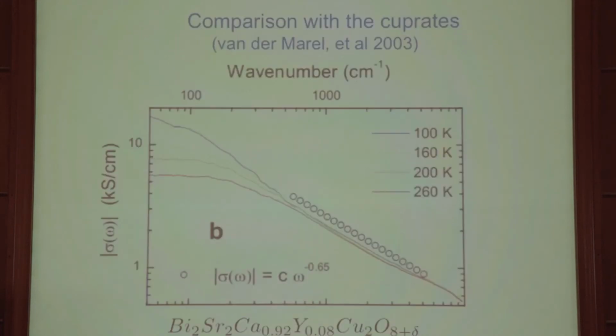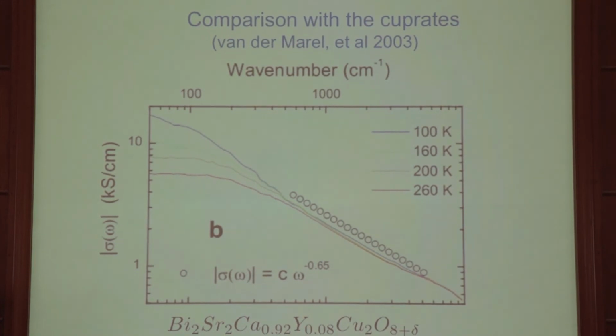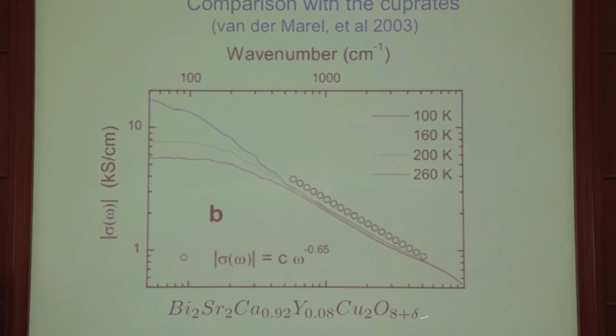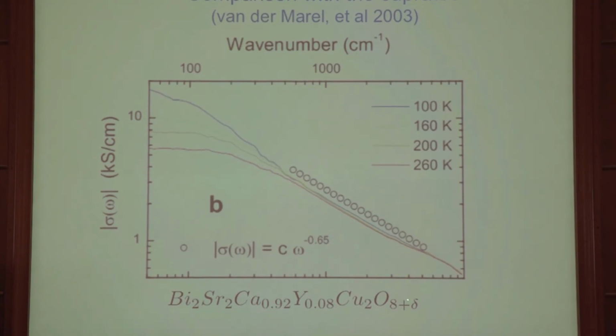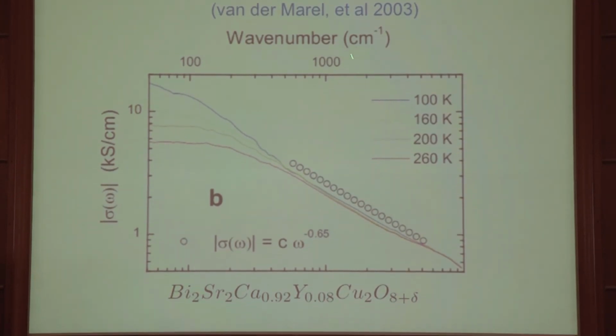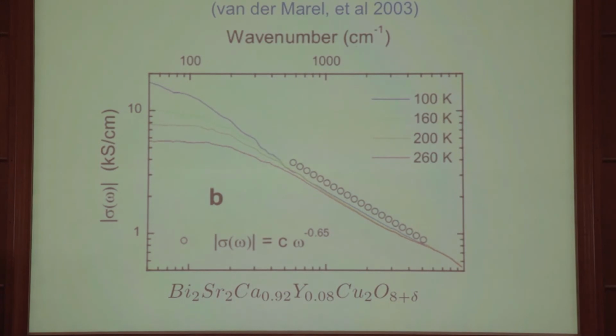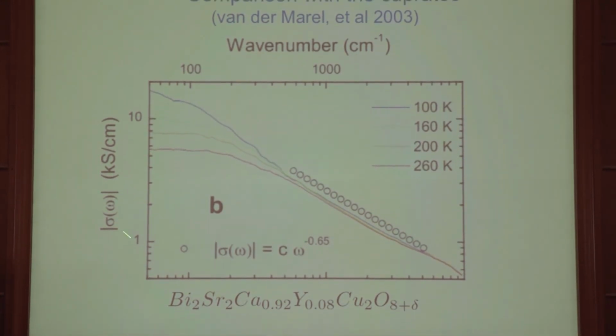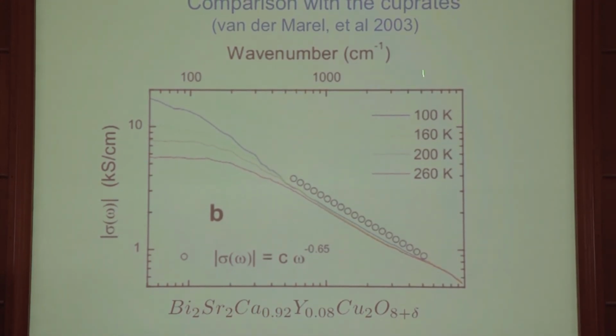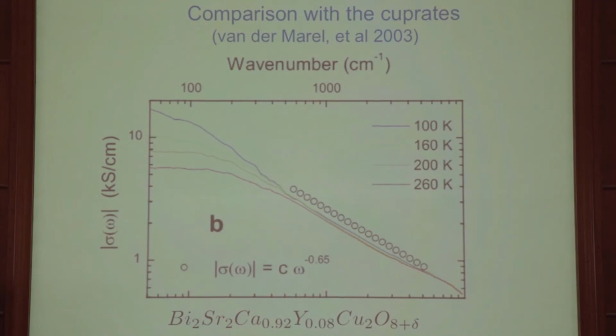But then you look at the cuprates. And now this is real data taken on a particular cuprate of bismuth, strontium, calcium, copper oxide, commonly called BSCCO. Data taken in 2003 by van der Marel. He plots the absolute value of the conductivity as a function of frequency for various temperatures, and these are all above the superconducting transition. This material has a superconducting transition temperature of about 90 degrees. So he's looking at the normal phase, and we were looking at just normal conductors.